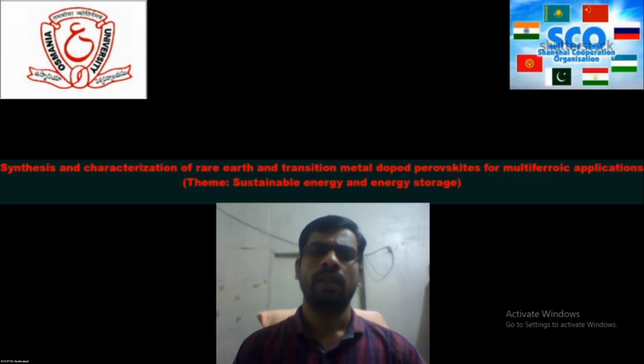Magnetization of LaFeO3 bulk and thin film perovskites are found to be 0.44 emu per gram and 60 emu per gram respectively. Remanent polarization of NdFeO3 bulk and thin film perovskites are found to be 0.01 microcoulomb per square centimeter and 5 microcoulomb per square centimeter respectively. Activation energy of mobility of charge carriers of LaFeO3 bulk and thin film perovskites are found to be 0.20 electron volt and 0.96 electron volt respectively.